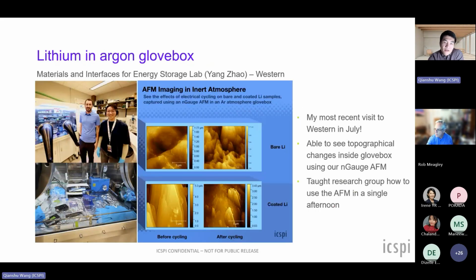A recent visit also was to another local university, Western University in Canada. I was visiting Professor Yang Zhao. He was very curious to see lithium samples actually using AFM. He needed to look at these lithium samples within a glove box. He wanted to see and compare coated versus bare lithium samples. And he wanted to test and see what the effects of electrical cycling were on these samples and compare the performance of a coating. So we were able to set up our AFM, our nGauge AFM, inside the glove box and to take these images. These were all done in an argon atmosphere glove box. And I was even able to teach his research group how to use the AFM as well in a single afternoon.